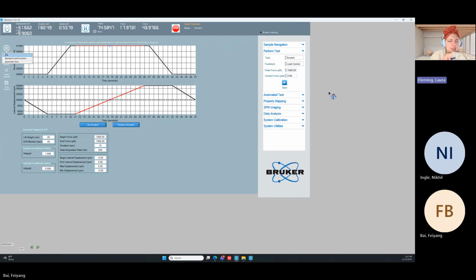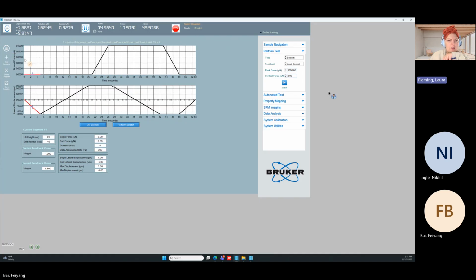Okay, the next standard load function is where things start to get a little bit more complicated. Here, this should look very similar, right? This part, we're loading while we're constant in the x. We're holding in z while we scratch. We're unloading and then moving the scratch back to 0. But there's an entire 20 seconds of test before that. This is how we get our tilt correction, so that we have accurate normal displacement results.